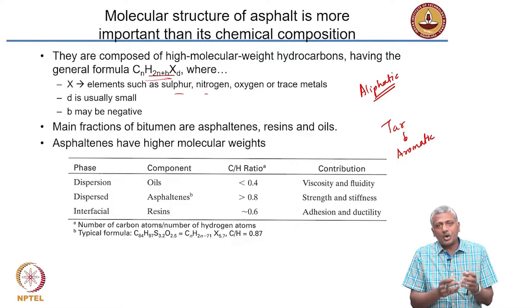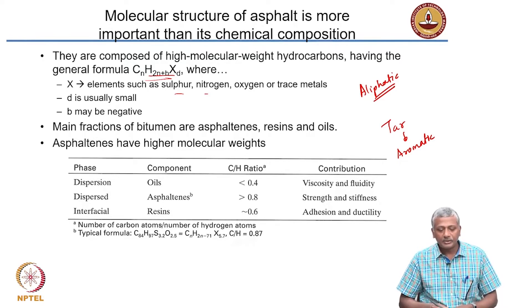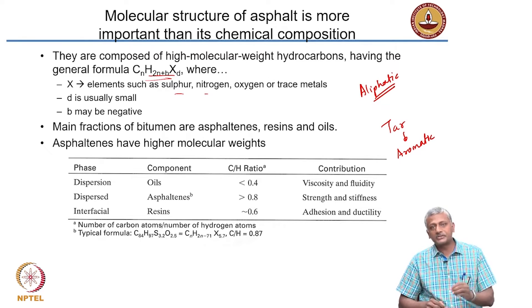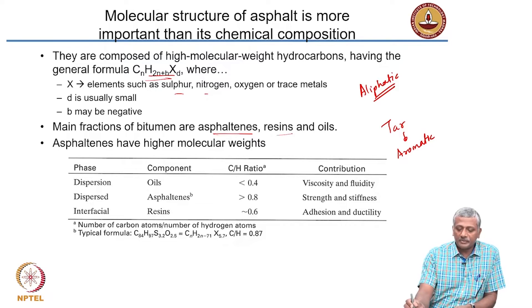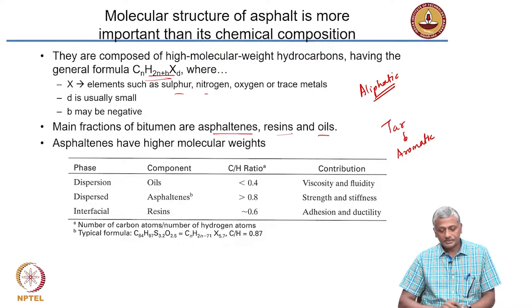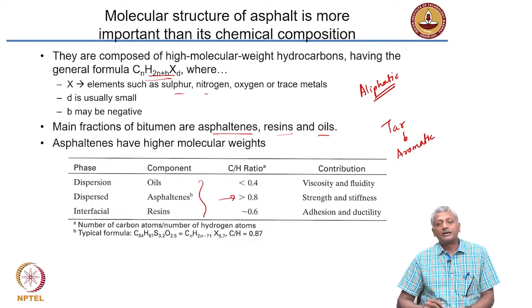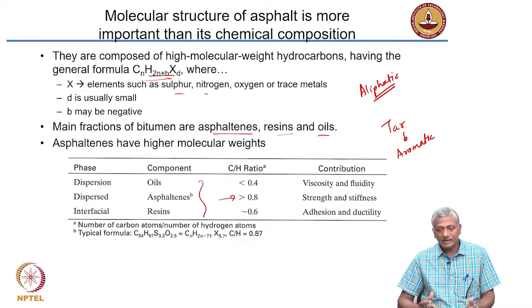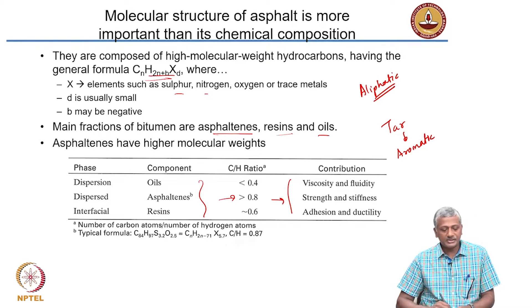Asphalt is not as uniform as it looks. It has got a lot of features which need to be looked at carefully to really understand the composition of the asphalt or bitumen. This composition is made up of asphaltenes, resins, and oils. These materials differ in terms of the type of hydrocarbon or the carbon-to-hydrogen ratio in the polymer molecules.